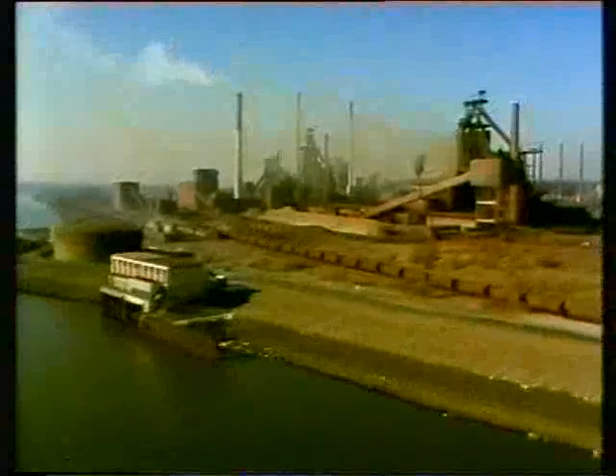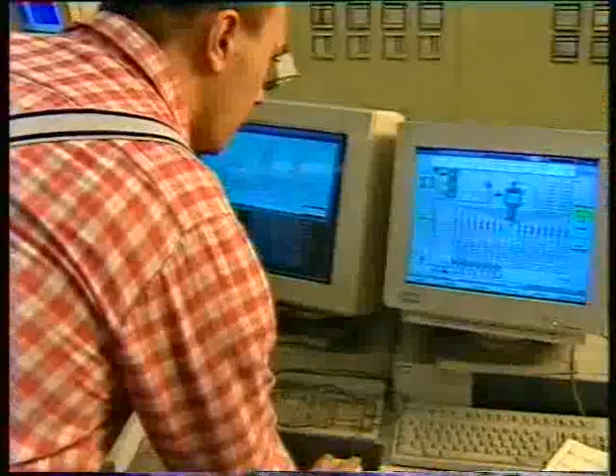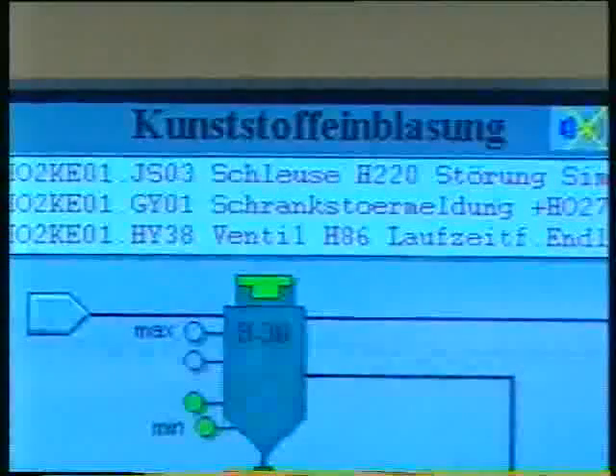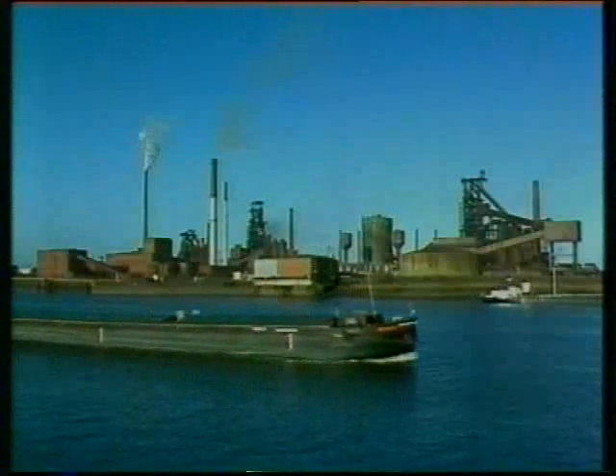Mixed plastics can also be of great service in the production of pig iron. Injected into the blast furnace, the agglomerate reacts with the iron ore, removing the oxygen from it. Pig iron forms and can be run off. In this process, plastic replaces heavy oil on a 1-to-1 ratio, thus helping to conserve valuable resources.